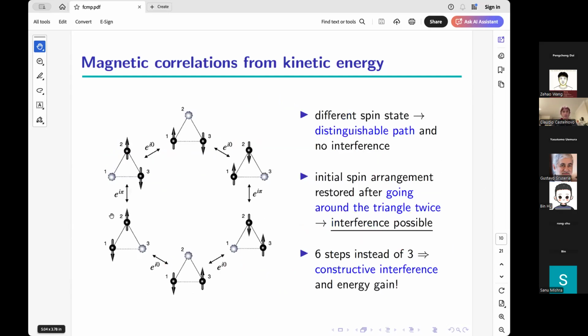On the other hand, if we have antiferromagnetic arrangement of the spins like shown here, let's start, I presume you can see my cursor, from the triangle that I'm highlighting at the moment. And then let's do the same process, move the hole around. Now the spins of the two electrons are oppositely aligned. We hop once, exchange 1 and 2. We hop a second time, exchange 2 and 3. We hop a third time, exchange 3 and 1. We got the hole back to the original position, but the two spins now have traded positions, so they are no longer the same state, and interference is not possible.